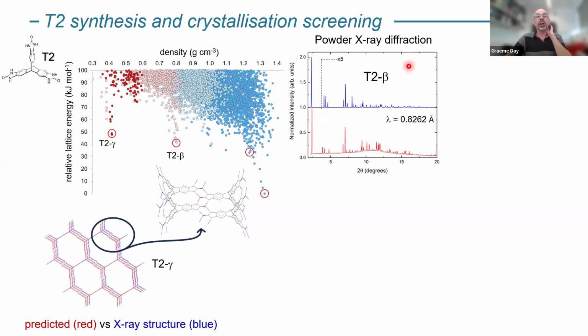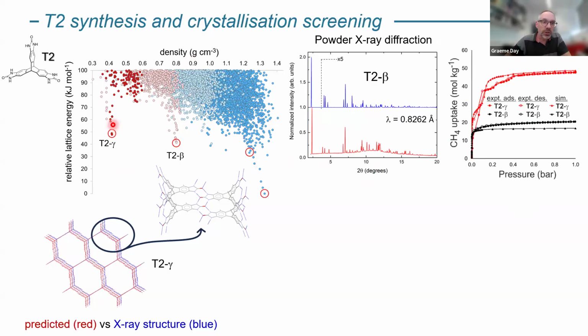A nice thing about having the predictions is that we can simulate powder diffraction data from each predicted structure, which lets us very quickly match things up with powder data we get from the lab. So that lets us accelerate the experimental screening as well. So this structure here was the one we were interested in. It has this red colored dot, it has the methane deliverable capacity in the range that we want. It is one of the structures that we find experimentally here.